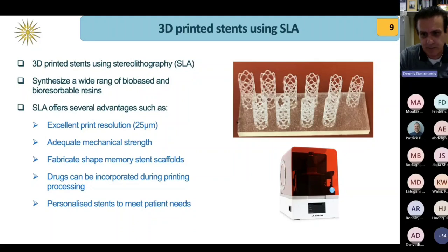And the reason that we moved to SLA was that it offers several advantages. It has excellent print resolution, can go down to 25 micrometers. We could develop our resins to offer adequate mechanical strength and also fabricate what we call a shape memory stent scaffold. At the same time, we could incorporate drug substance during the printing process, as I mentioned before. But we could also print plain stents and apply the drug on the surface.